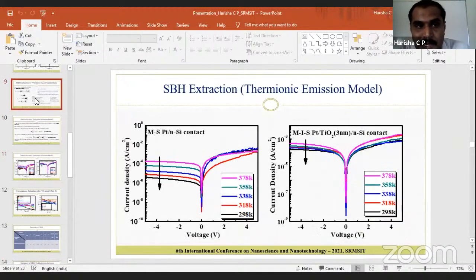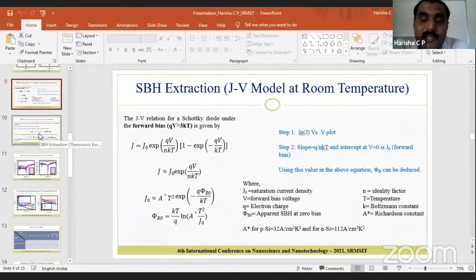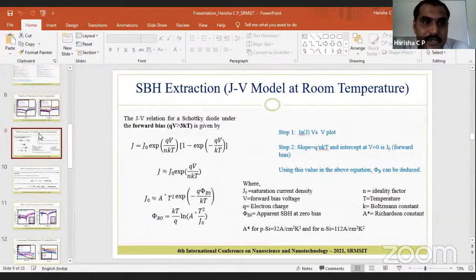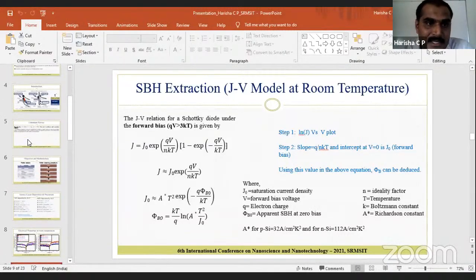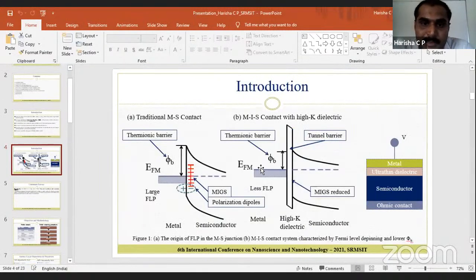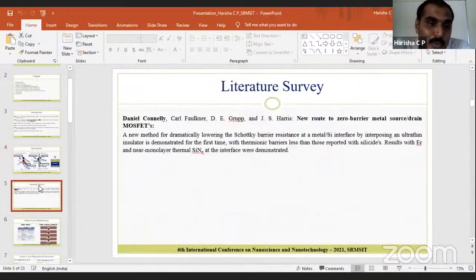Yes. Earlier research works have shown that inhomogeneity could be one of the reasons for the Schottky barrier height. But the fundamental purpose of keeping a thin dielectric layer between the metal and semiconductor is to passivate the surface. So the passivation effect is the biggest factor which will reduce the Schottky barrier height. But the inhomogeneity will be there. It is obvious in both the MS contacts as well as MIS contacts.